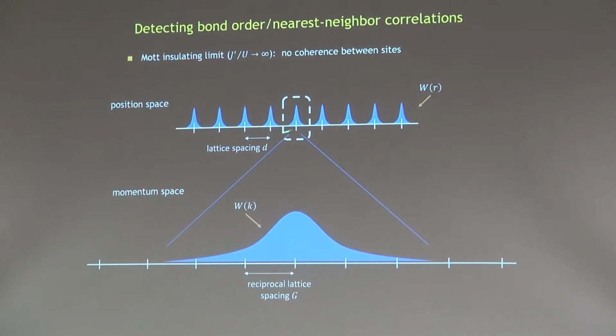If I examine this position space distribution of atoms in momentum space, what I see is the following. One single lattice site diffracts, right? So it expands from position space where it was confined to momentum space, so it expands outwards. And we see a momentum space distribution that by necessity spans several reciprocal wave vectors because the atoms are tightly confined within the unit cell. And this same momentum space distribution emerges from each of the sites within the lattice, but because the atoms are totally incoherent from one site to the next, the overall momentum distribution is just the incoherent sum of many of these Gaussians. So they just lie right on top of each other. You see this big Gaussian distribution.